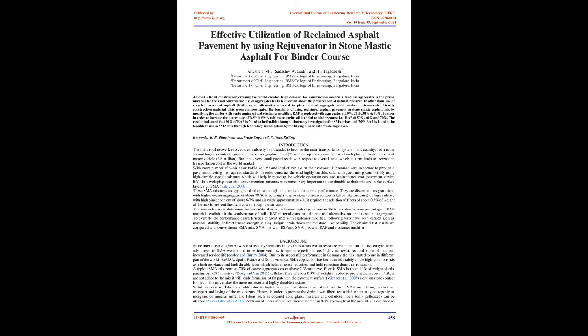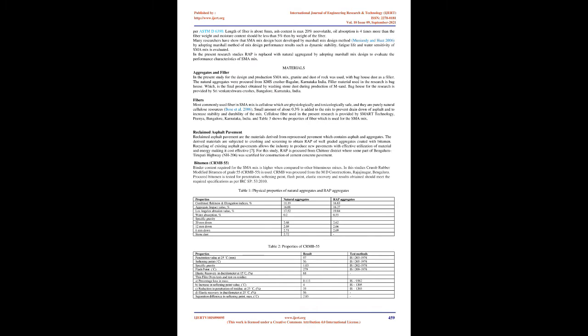SMA, Vale et al. 2006. These SMA mixtures are gap-graded mixes with high structural and functional performance. They are discontinuous gradations with higher coarse aggregates of about 70 to 80% by weight to give stone-to-stone contact, a skeleton-like structure of high stability, with high binder content of about 6 to 7% and air voids of approximately 4%. It requires the addition of fibers of about 0.3% of weight of the mix to prevent the drain down through the air voids.